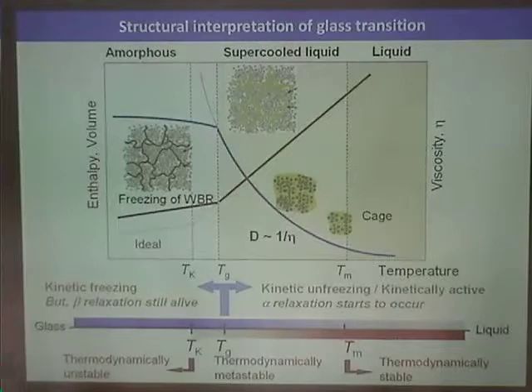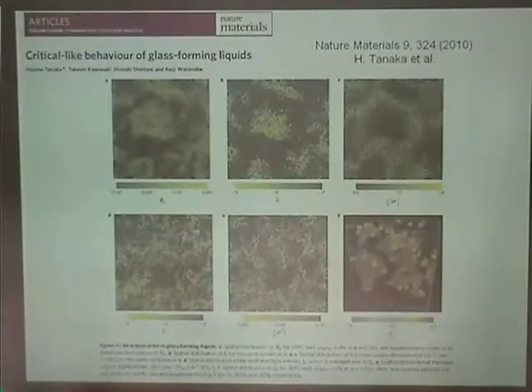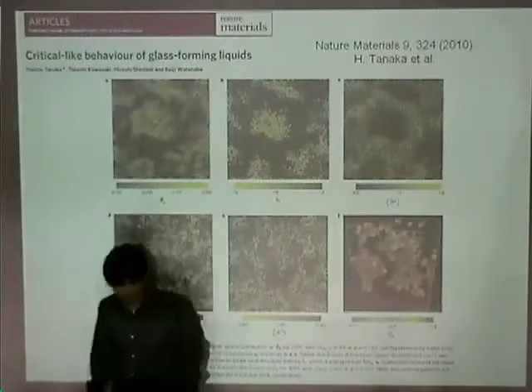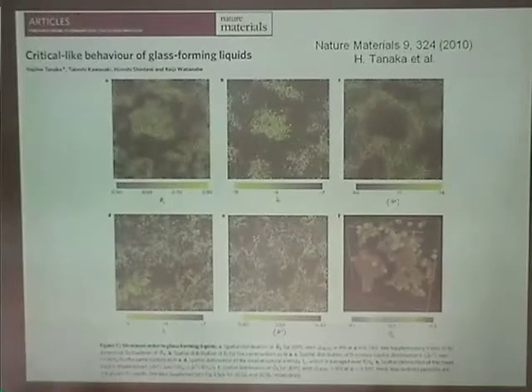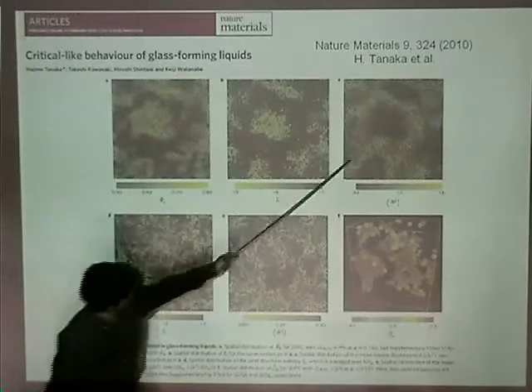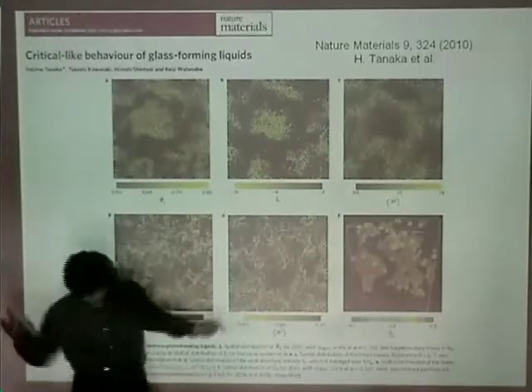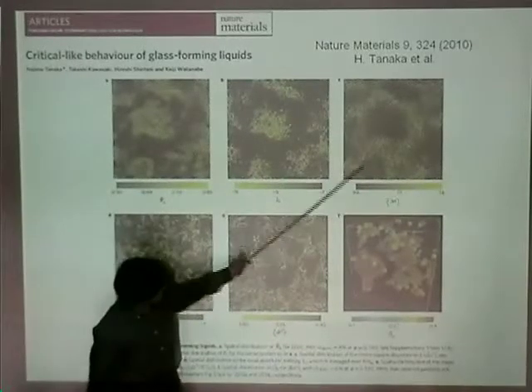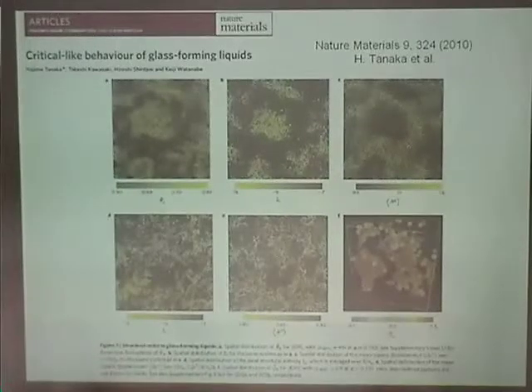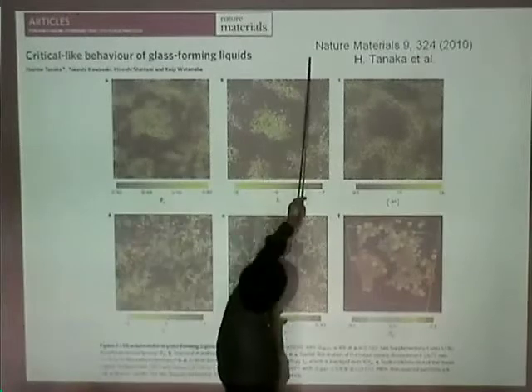So like recently, this was reported by Professor Tanaka. He claims that the dynamic heterogeneity is strongly related to the static heterogeneity. This was published in 2010, so very recently. I don't know the details of the result and the simulation treatment, but in this region the dynamics is very active, and this is a very immobile region. Here there is a correlation between dynamical heterogeneity and orientational correlation functions. If you want to understand the details, please see this.